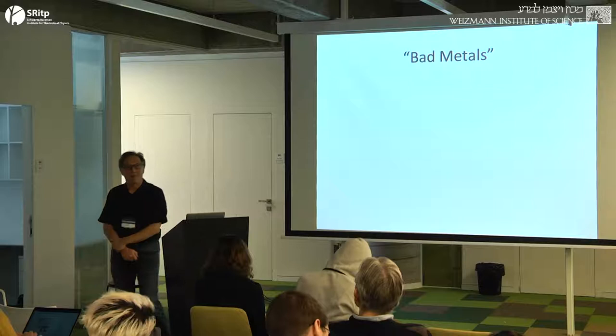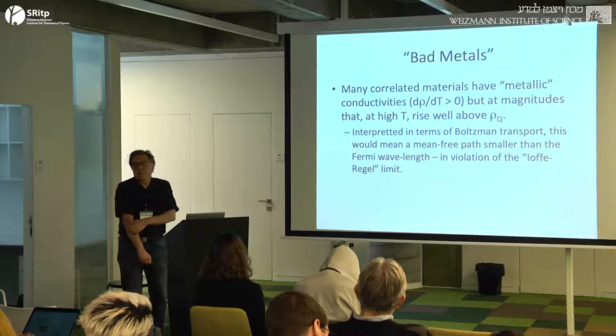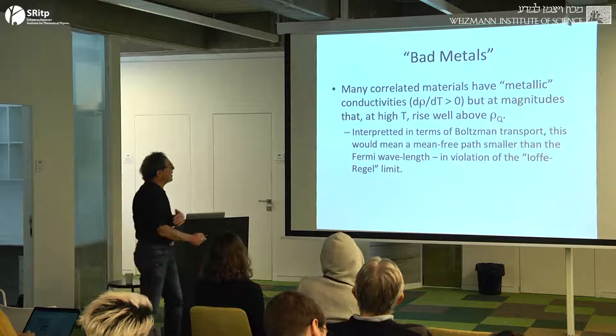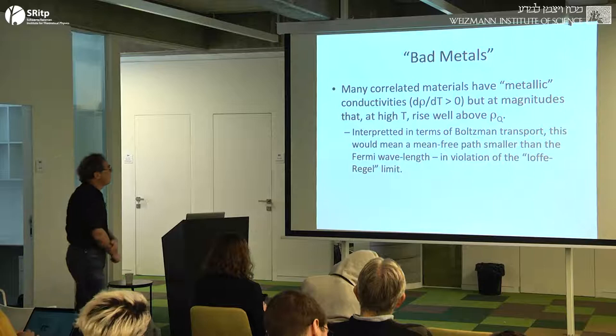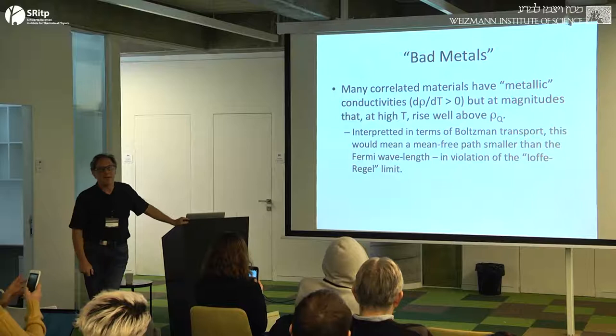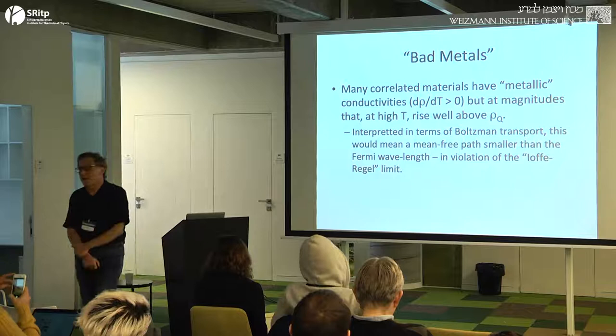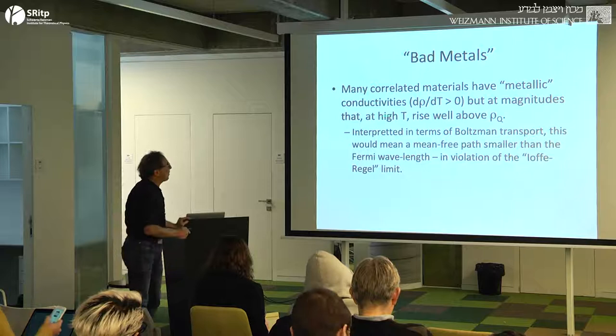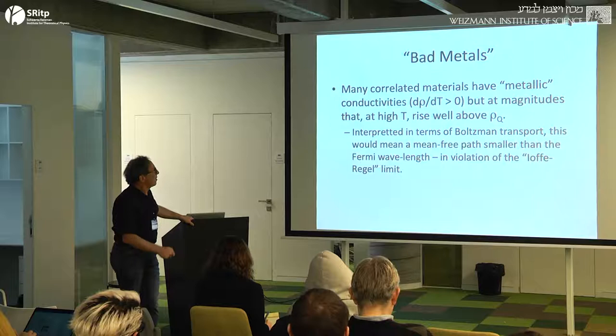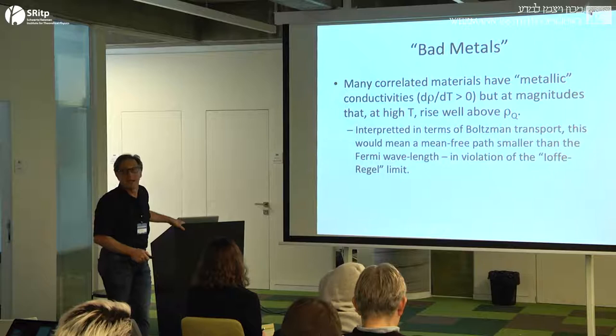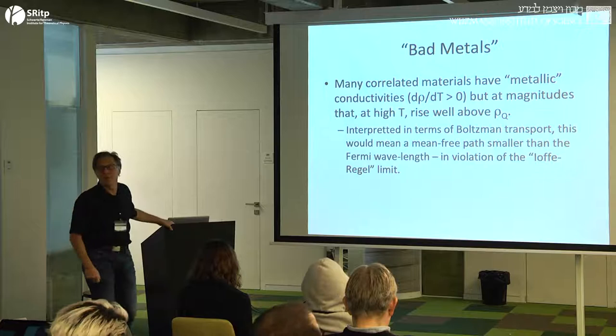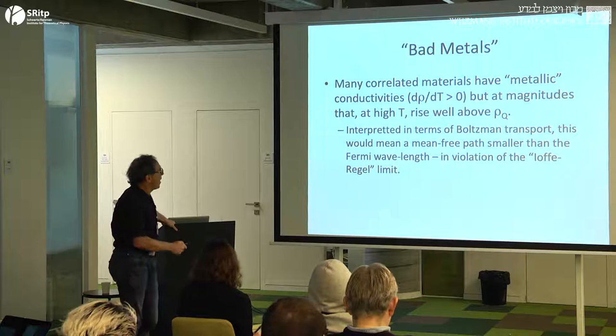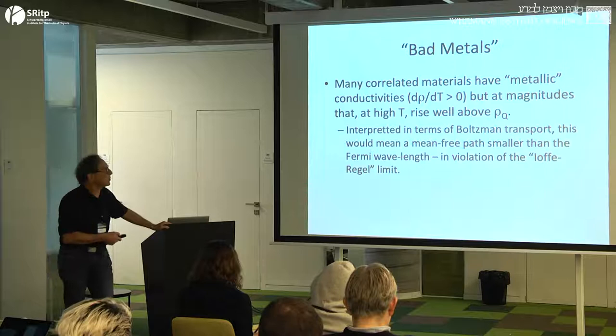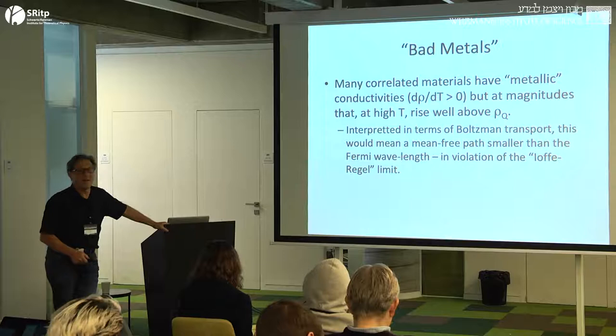Now, what became painfully obvious with the discovery of the cuprates, and now seems to be a rather ubiquitous feature of many, but not all highly correlated electron systems. Certainly the heavy fermion systems that I just showed you are also strongly correlated, but many strongly correlated materials have resistances that are metallic in the sense that the resistance continues to increase without any sign of saturation at high temperatures, but at magnitudes that rise well above this quantum of resistance, and where if you were to force this to be interpreted in terms of Boltzmann transport theory, it would mean mean free paths that are much smaller than the Fermi wave-length.